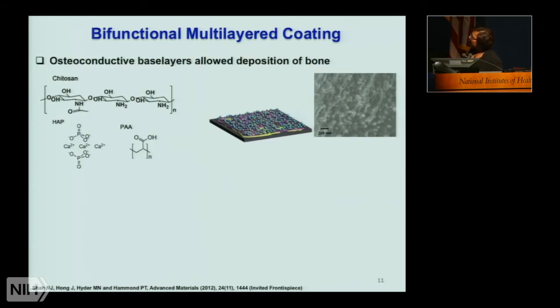So in our work, we've been looking at ways in which we could generate an osteoconductive base layer because we're no longer working with a degradable membrane, but with a stiff, rigid material like titanium or PEEK, and we want to make sure that we have an environment on which bone cells can grow and adhere. So in our case, that base layer is going to be composed of a chitosan-wrapped hydroxyapatite nanoparticle that has a net positive charge and will be alternated with polyacrylic acid. We just put down a few layers of this material. We can think of it as a system which doesn't degrade over the lifetime of our release film, but will be absorbed or resorbed by cells over a longer time period.